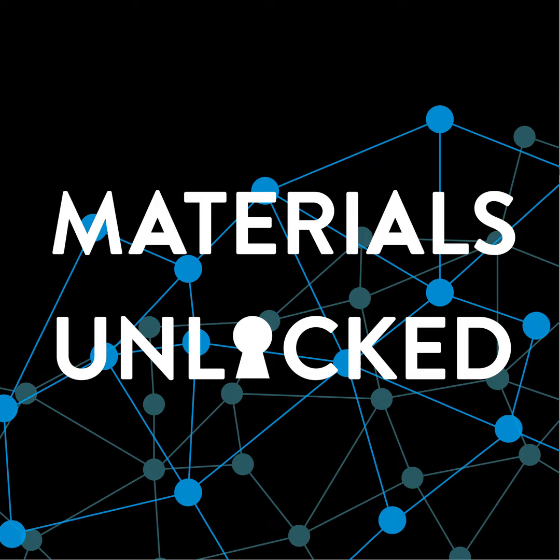Yep. So with the steels that we're looking at the moment, one of the things we've discovered is that depending on the build parameters that you use, so depending on the laser power and the travel speed, that determines how much heat you put in, that determines how it cools down and solidifies, and that determines then which phase you get at room temperature. So we've actually been able to build structures where we can distribute this weak ductile phase and this strong brittle phase in different regions and get different mechanical performance out of the component as a whole. So if you just had the weak ductile material, it yields quite early, but it can cope with a lot of deformation.